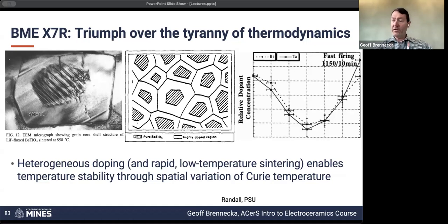Great question, Yang. So I'm assuming that you're talking about the phase transition associated with this transition from cubic to tetragonal. So we'll get into that a little bit more, but for right now, I'll just point out that for barium titanate, so pure barium titanate, without any of these dopants, the lattice parameters are roughly 1% different. So if you go from cubic to tetragonal, it's about 1% strain between the A and C dimensions, which is not nothing. 1% strain is a lot for a ceramic, but it's relatively easily accommodated by forming these twin structures. And so for barium titanate, that amount of strain associated with that phase transition is usually not enough to lead to cracking. You can accommodate it by just forming these twins.